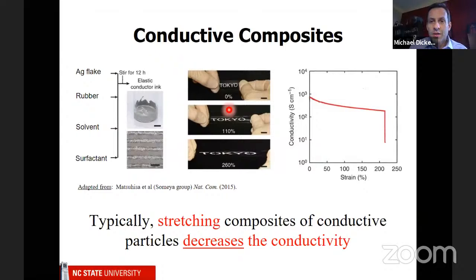And I need to tell you something about composites like these. Normally with conductive composites, for example, if you take silver flakes, like little pieces of silver, and you mix it with rubber, they're typically not conductive at all. However, there are a few groups that have come up with some very clever solutions by adding just the right mixture of stuff. You can make these things conductive. So this is what the silver ink looks like, and you can see it's stretchable. But one of the problems is that if you measure the conductivity, you see it actually gets lower. So that means the resistance is going way up.